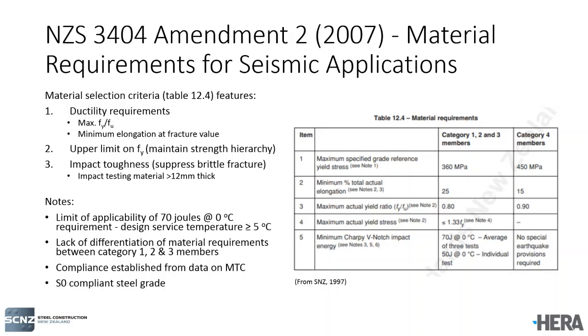Unfortunately, the standard doesn't say what to do if your design service temperature is below that. For example, you're in Queenstown, it's an external structure. You could be operating at -5 as your design service temperature. Another point to note from the table 12.4 requirements is that there is no differentiation between Category 1, Category 2 and Category 3 members. At the time when Amendment 2 was published, there were no steel grades anywhere in the world that actually complied with the requirements of Table 12.4, and so compliance with the requirements was required to be established from the data on a material test certificate.